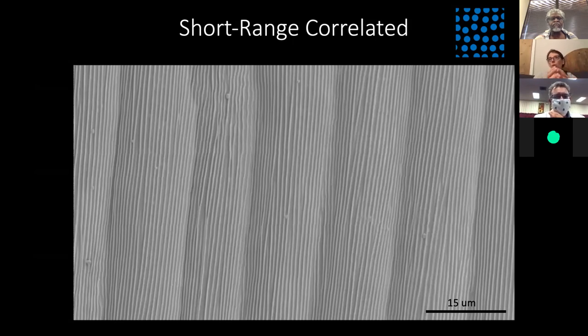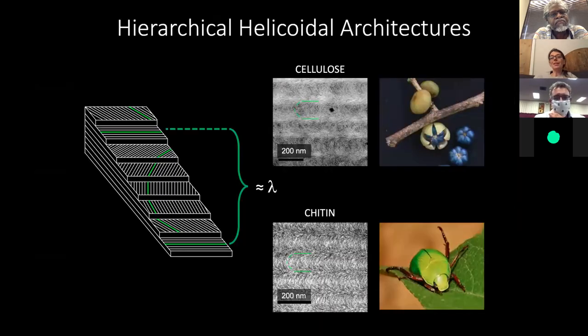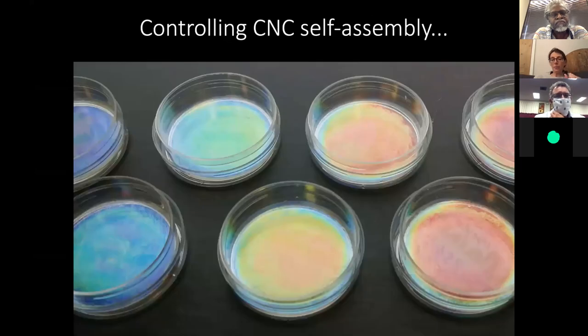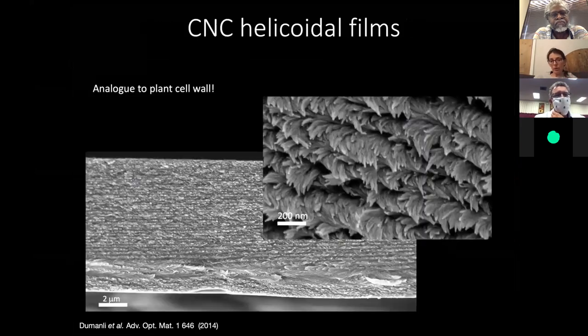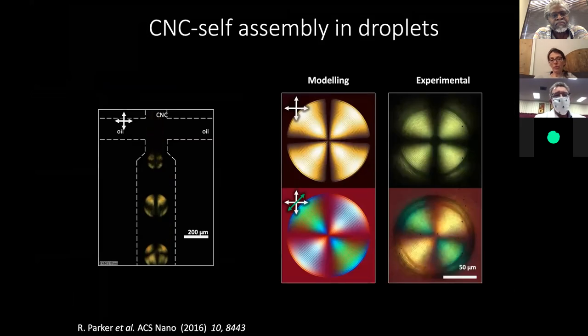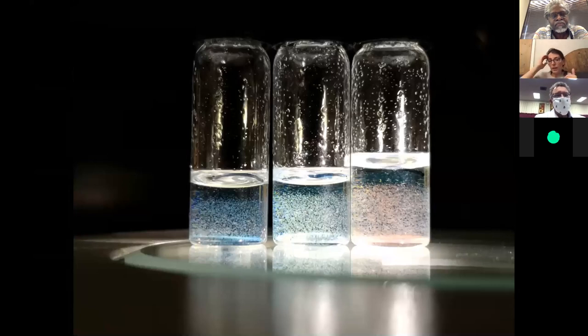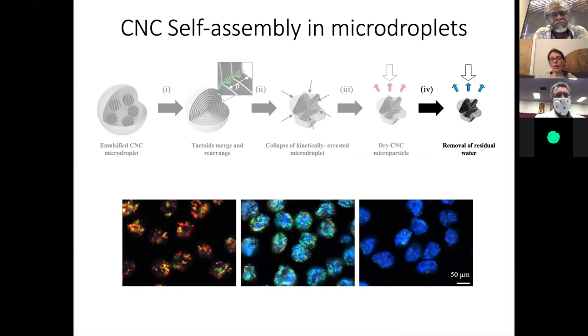And then you have the second step, which would be the assembly. But if you compare it with the equivalent in the pigment industry, the pigments that we make with structural color would be called effect pigments. And the effect pigments that you have today, like here we propose to use cellulose to make them, so to have something like this one, that are 100% cellulose. Obviously, in order to reach that, we need to make the cellulose nanocrystals and assemble them into droplets. So it's complicated. But what is industrialized now is that people at BASF or Merck, they get mica.